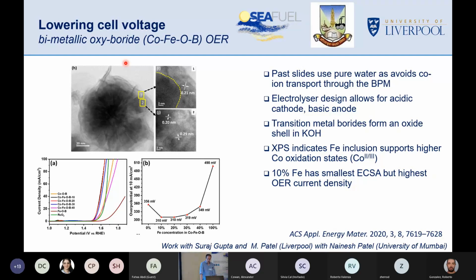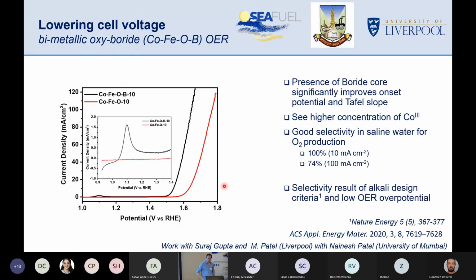So we do a little bit of work on oxygen evolution catalysts. This is actually done a lot with Maulik Patel at the University of Liverpool and his colleague Suraj Gupta, and also the team at University of Mumbai. And we're interested in boride catalysts. So you take a boride catalyst. Here we've got a cobalt iron oxyboride. You put it into your electrolyte, and this would be a high pH electrolyte, and it forms a nice oxyhydroxide shell. You get a nice conductive core. And you can see that you can change the metal content. We can get particularly high activities now for OER at high pH, and we can compare our behavior here to a standard non-boride catalyst of just the oxide, and it's much improved.